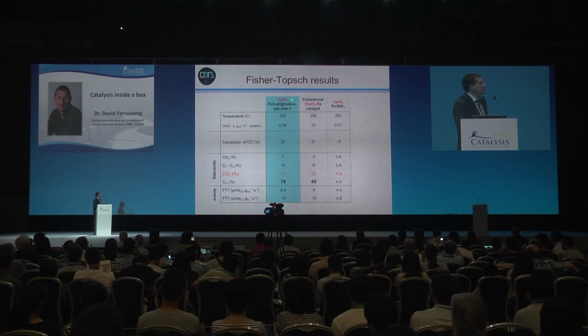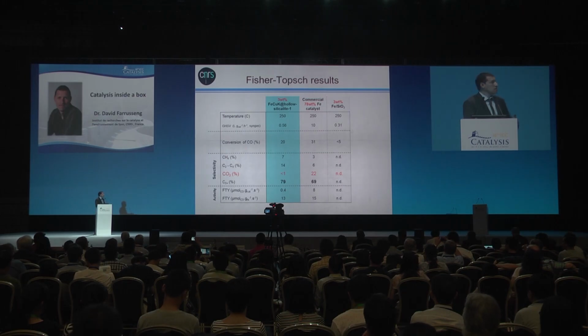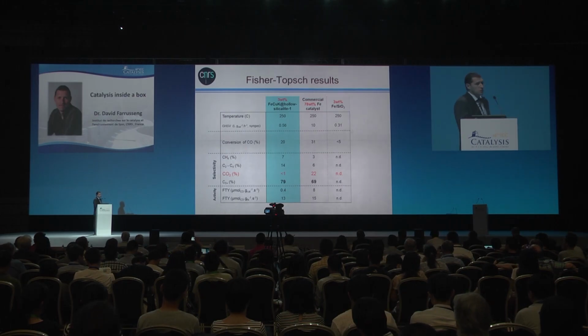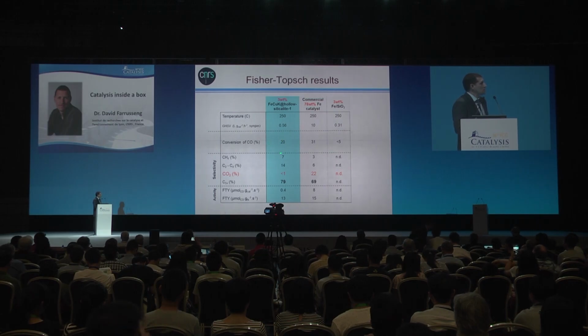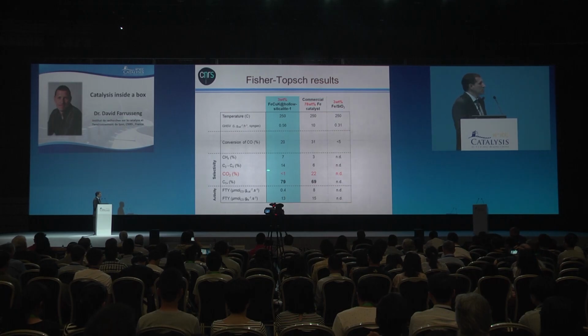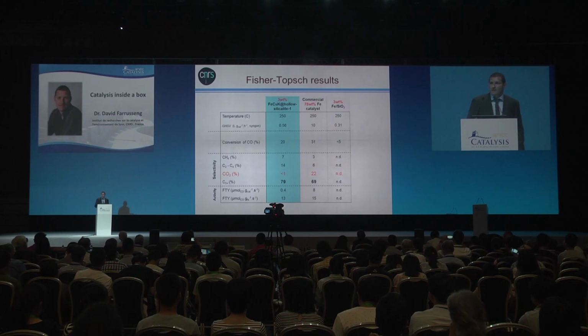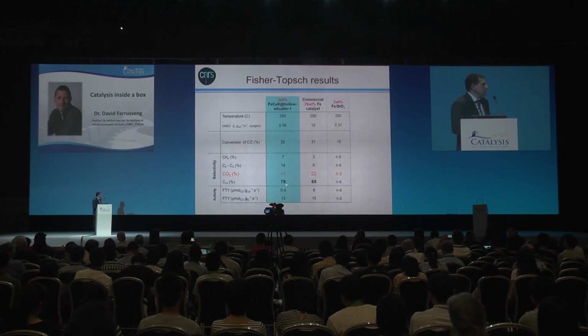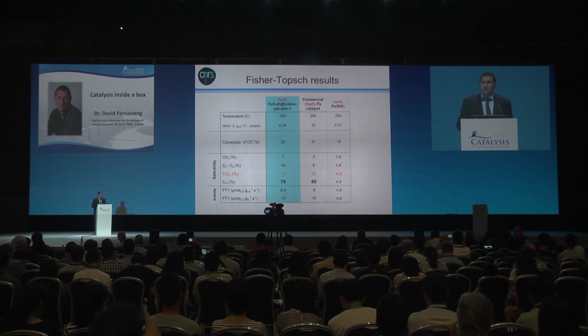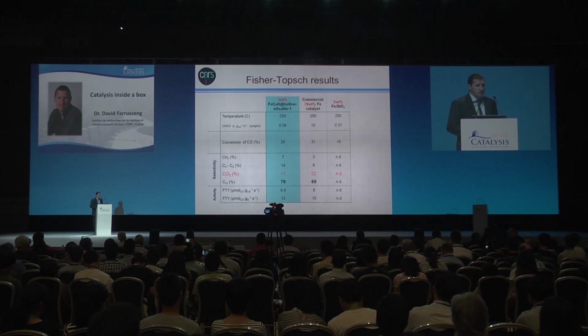For our catalyst, which is only loaded at 3%, doped with copper and potassium, at 20% of conversion, what we have is a bit more light alkanes, but look at that, we don't have any CO2. It was really amazing, and we were wondering why we have that result. And it results in a liquid hydrocarbon selectivity of about 80%.